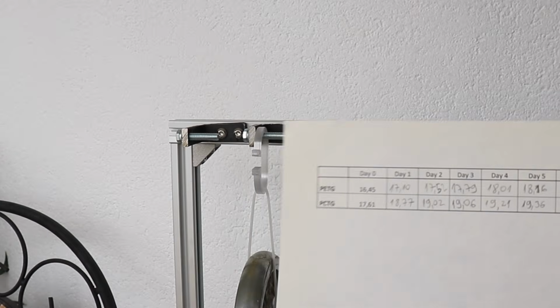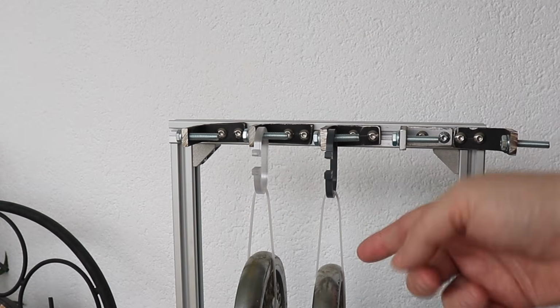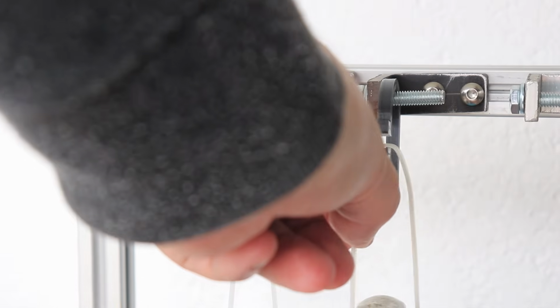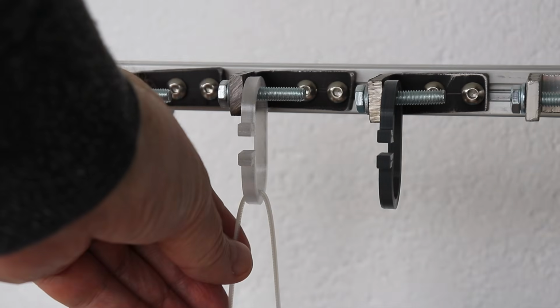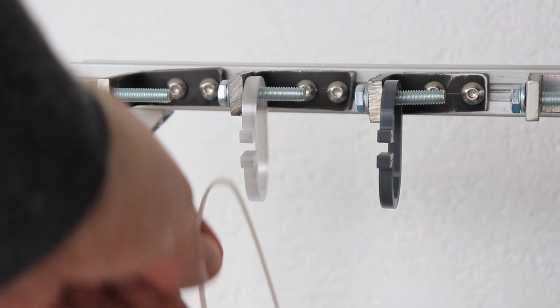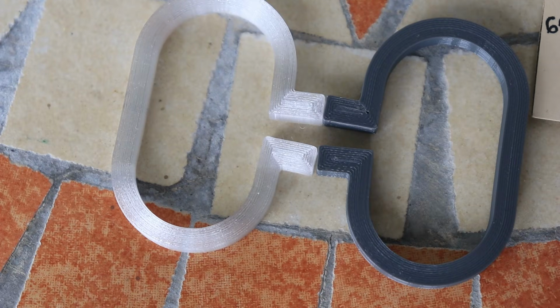I already measured everything, and I also want to record the removing of the load. Interesting, during the test the PCTG deformed more, but now when I remove the load and wait 10 minutes, I can see very minimally more permanent deformation on PETG compared to the PCTG.